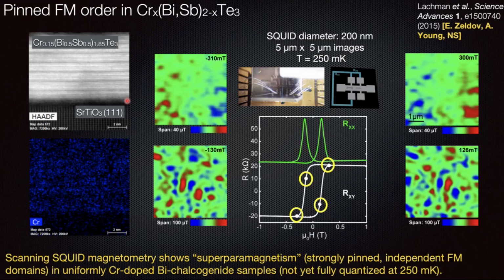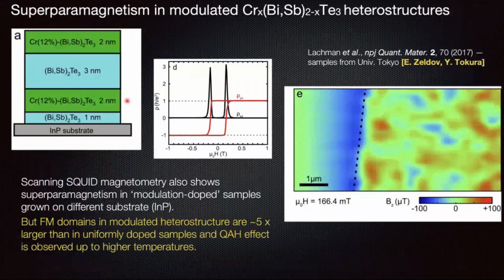Here, when Eli used scanning SQUID magnetometry to measure the evolution of the magnetic state as you reverse the magnetization, as you go from Chern number equal to -1 to +1, what he found was that the magnetization is strongly pinned. It's very inhomogeneous, and it's sort of little unconnected domains, if you will. Later on, Eli looked at modulated heterostructures from Tokura's group, and things did improve. So the domains got larger, but nonetheless, the overall behavior was still the same.